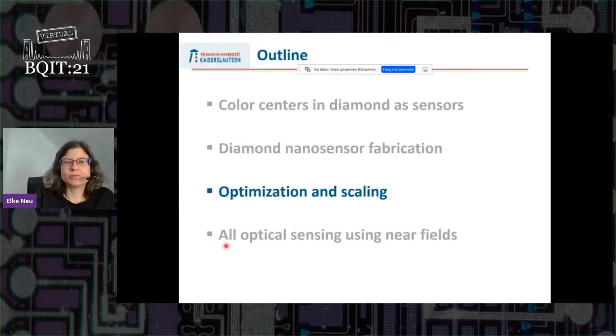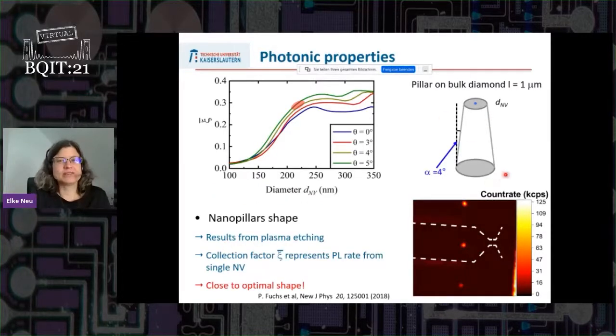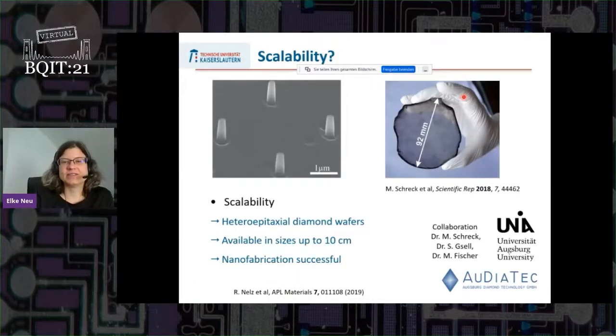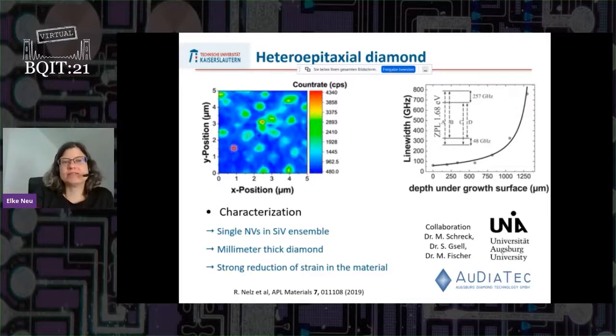And I want to say some words about what we can do about optimization and scaling. First, you might have realized the pillars are not perfectly cylindrical. If you simulate it, this little bit of a truncated cone that we have also works very nicely, considering the photonics. And the second remark I want to make on this is that we are now trying to scale this process up. So far we are processing very small diamonds of just some millimeters, but in 2018 the group of Matthias Schreck in Augsburg presented the first single crystal diamond wafer. This is done by so-called heteroepitaxial diamond, and we have also used this to make such pillars. It works very nicely, and this material is now getting pure enough so that we see single nitrogen vacancy centers here, these dots, in the material. So we are really hoping that in the next years you can also scale this up, make more diamond tips, larger structures, and so on, using the so-called heteroepitaxial wafer diamond material.